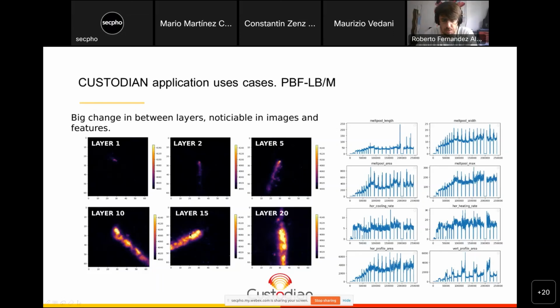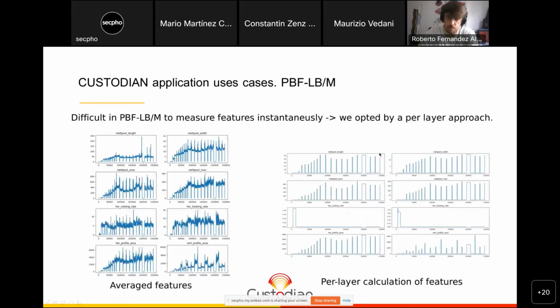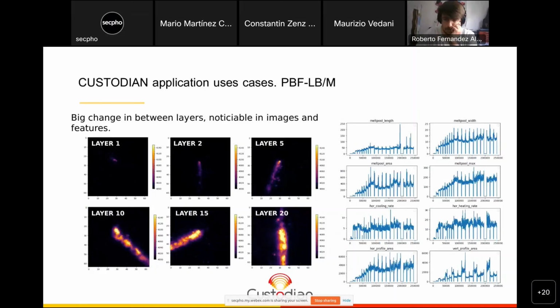We can see this in the different images, and we can also observe it in the different features. Here we have a collection of different features during these 20 layers, and we can see that some of them are very good to measure the heat accumulation. For example, the melt pool width, melt pool area, and also the melt pool maximum value and the profile areas are also good for measuring the accumulated heat in the process.